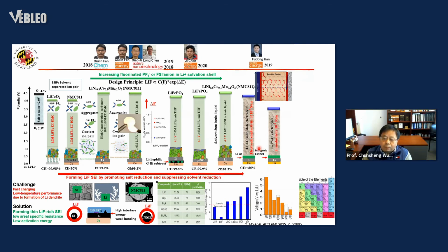And for the LPS sulfide electrolytes, they can potentially bring chloride. We know lithium chloride also has a very high interfacial energy with lithium, not as good as lithium fluoride, but at least better than LZO. So with LPSCl, they can reach high Coulombic efficiency.